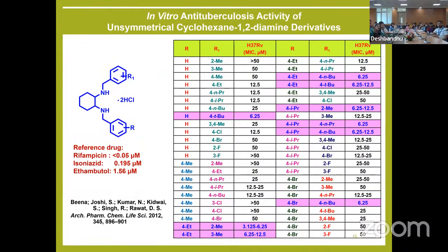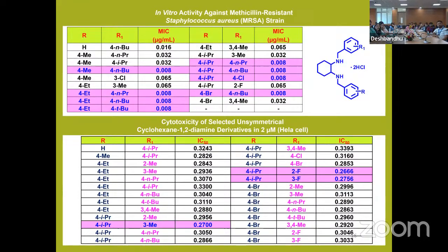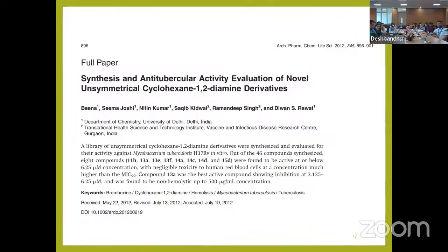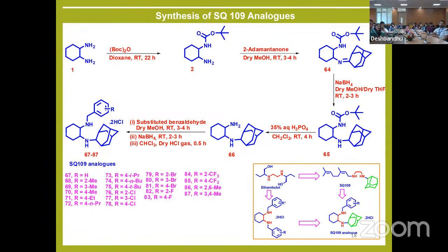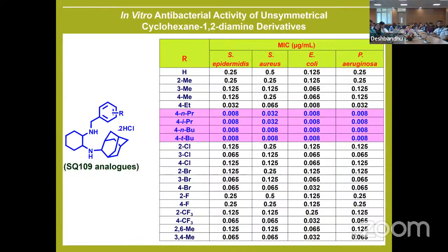Then we tested them against Mycobacterium tuberculosis, and ethambutol, the reference drug, has 1.56 micromolar activity, and our compounds were also equally potent. This work was published in this paper. Then we synthesized SQ-109 analogs, where we replaced one of the benzyl groups with the adamantyl group, and we could synthesize a series of compounds similar to SQ-109, and these compounds also showed very good antibacterial and